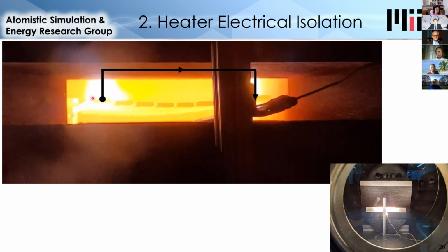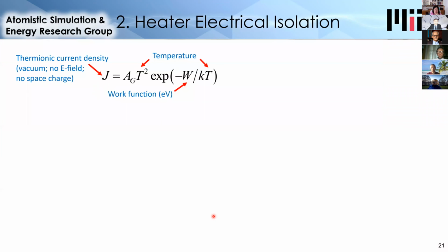But it also causes the heater and the lead rods to the heater to slowly degrade. They sort of melt because when electrons are emitted, the bonds between the graphite atoms become weaker. And so this was a problem both for heating and just the life of the system. And so we needed a way to prevent arcing. So first we tried to understand why it's arcing in the first place.